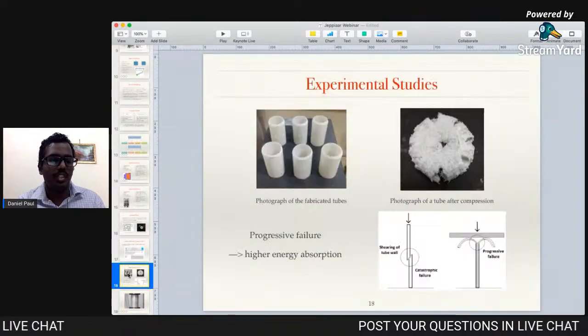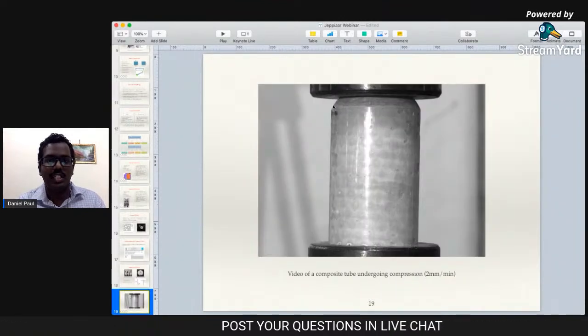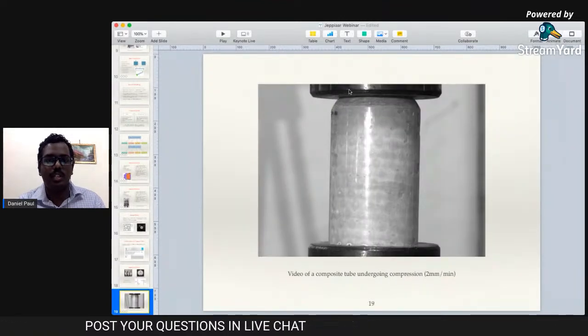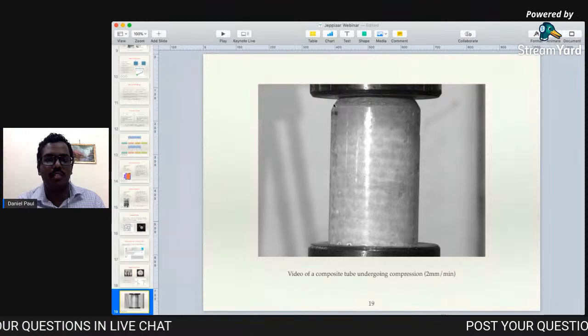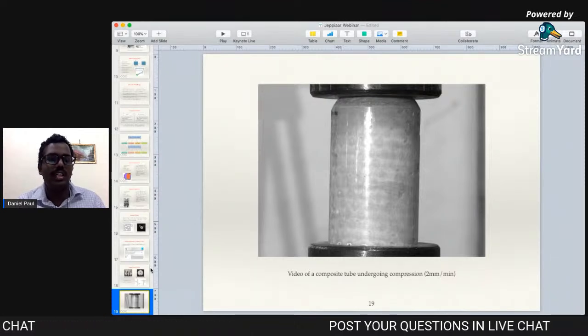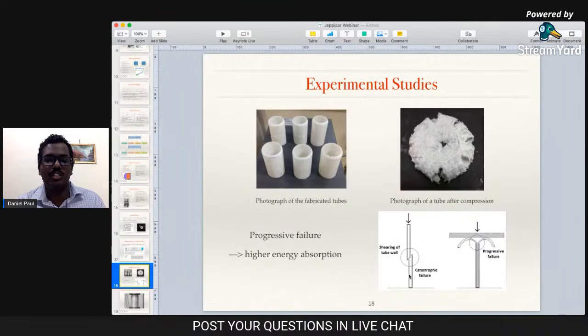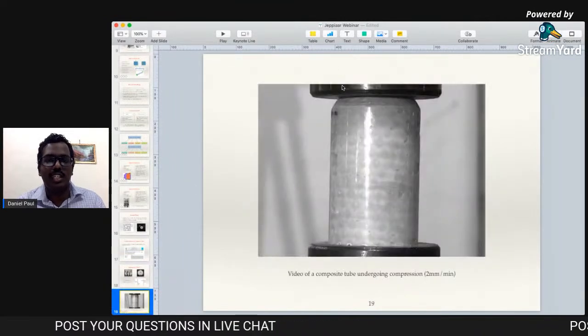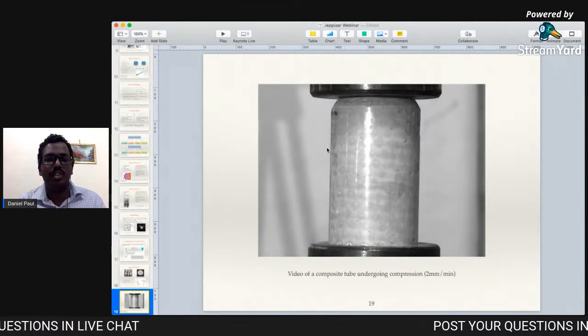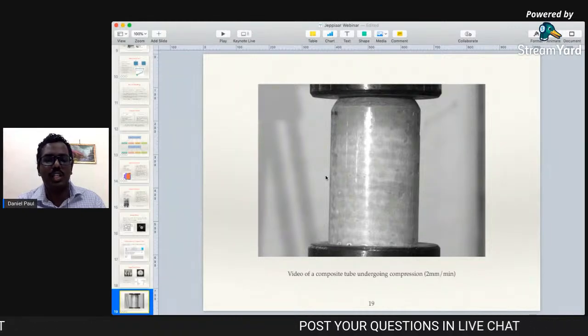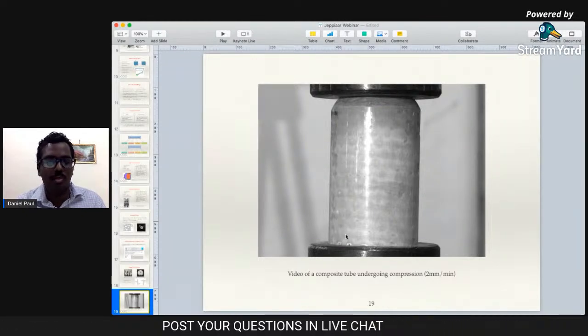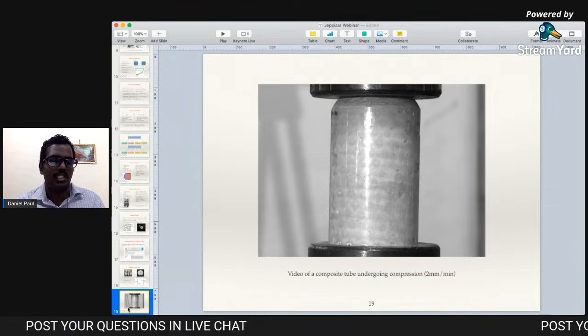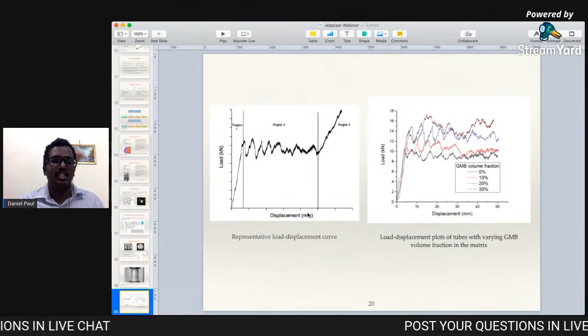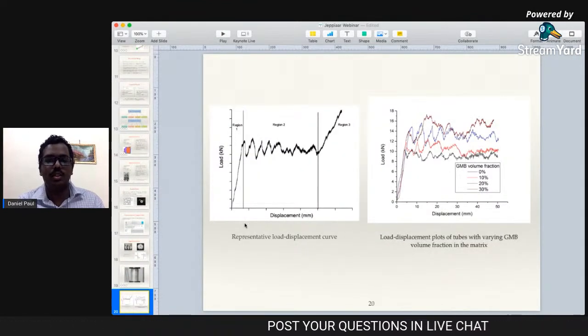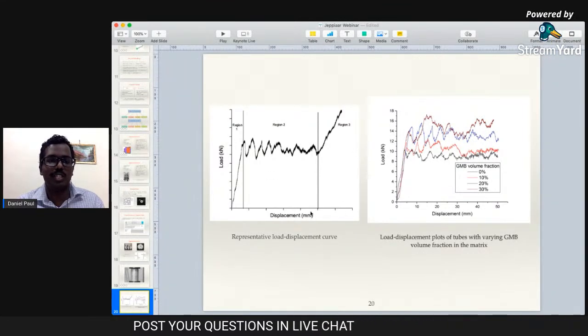So when you go back to this, you can see that the top end is chamfered, or smoothened in one way. If we do not do this, it again leads to a kind of catastrophic failure. So this chamfering initiates the petal formation, and then you can see it gradually fails until almost the entire length is compressed. And this is the representative and actual load displacement plots which we obtained from our experiments.